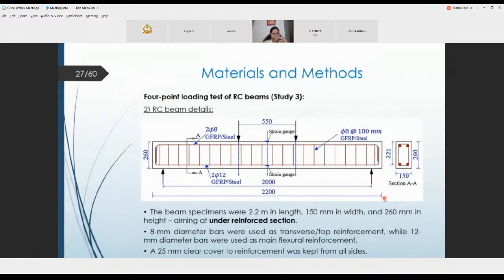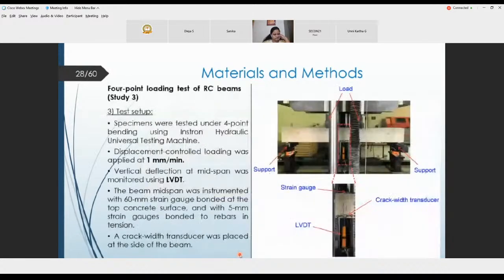The steel reinforcement, we're talking about a specimen of 220 centimeter, as a 2.2 meter specimen. And we talk here about a specimen 4-point loaded, as shown here. We used 8 millimeter stirrups and top reinforcement, and the clear cover was maintained at 25 millimeter level.